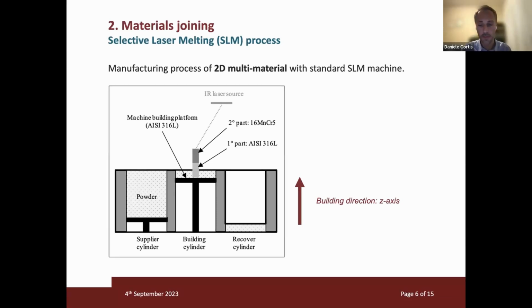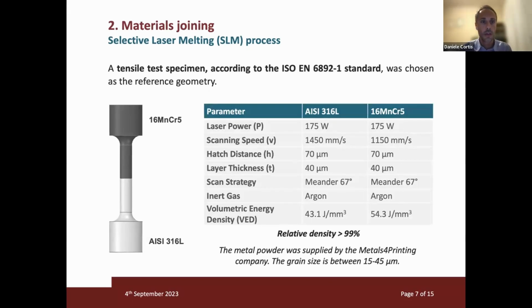In this case, we chose steel because there is a great affinity between these materials, and so we can start to study the junction without other uncertainties. As a reference geometry, we chose a tensile test specimen according to the ISO standard, because it's very simple to print a cubic specimen or a very thin layer of two materials. So we try to build something bigger, more robust, that can also be CNC machined after the building process, also to understand the machinability of the two materials joined together.